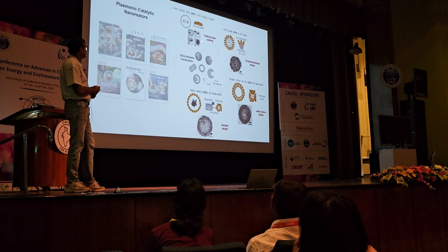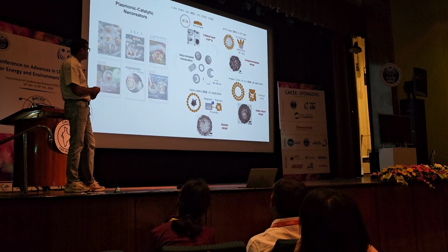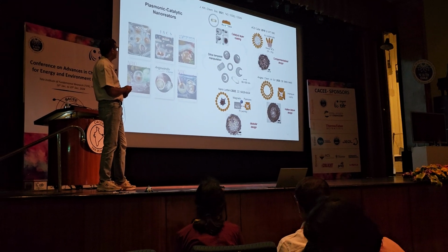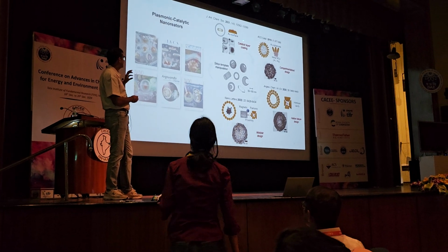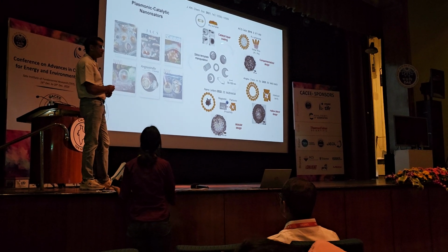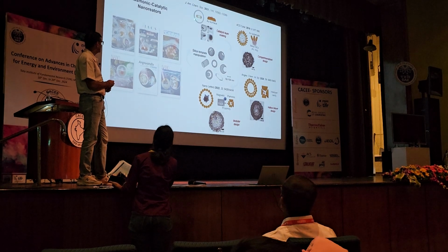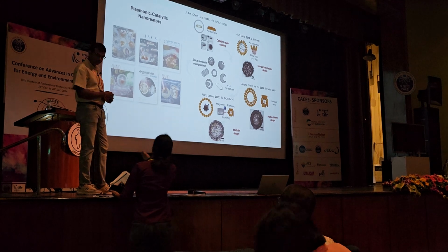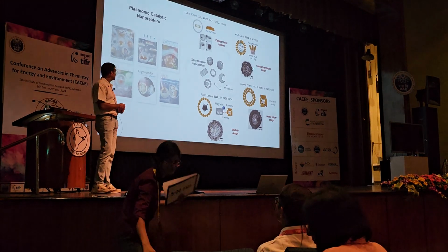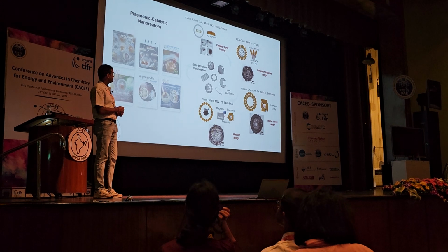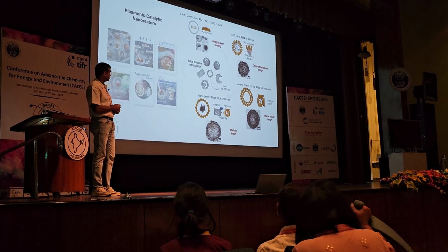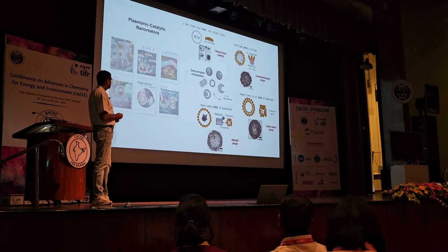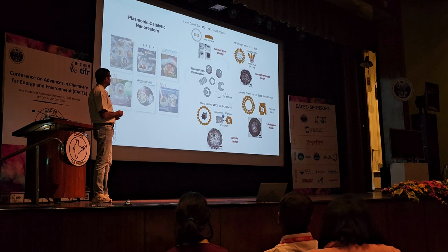Each nanostructure has its unique features in terms of controlling the reaction, because by this variation we have made choices of interfacing the catalytic compartment with the plasmonic compartment. So we can have different catalytic metal coatings on the plasmonic nanocrystal surface with atomic thickness precision. We can also compartmentalize plasmonic and catalytic compartments separately, which will protect catalytic nanocrystals nicely, and the light will be harnessed in the proximal plasmonic component and it will be transferred to the catalytic sites.